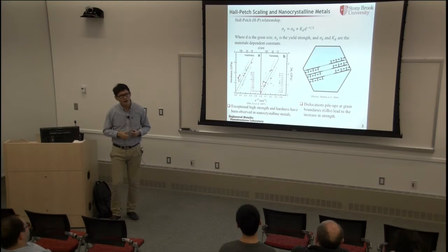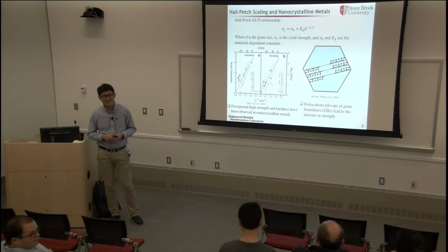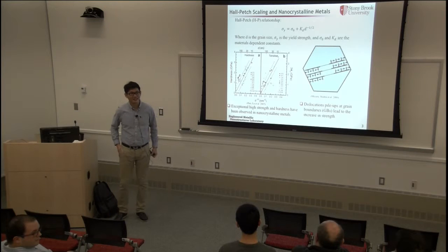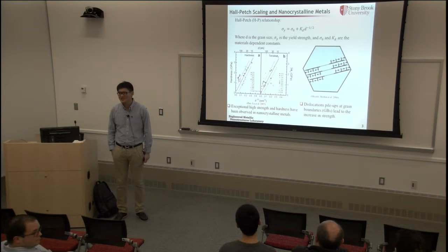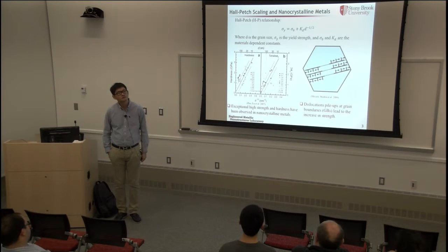Normal experiments are orders of magnitude less. Usually quasi-static is something like 10 to the -5. But with that said, a lot of these processes, these mechanisms, are thermally activated. So it has a similar effect as reducing the temperature to really low temperatures, because you're not giving a lot of these mechanisms time to occur.